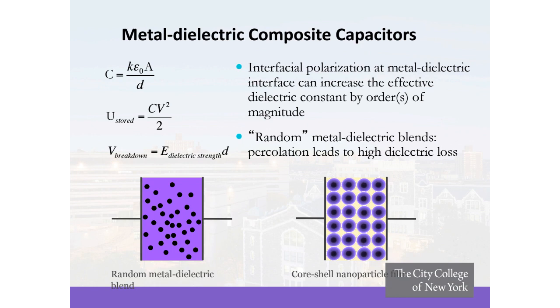We can use these metal core dielectric shell particles to form thin layers of very high dielectric constant materials for the purposes of fabricating high efficiency capacitors. The presence of the metal core in these particles allows for a very high polarization at the metal dielectric interface that increases the dielectric constant.